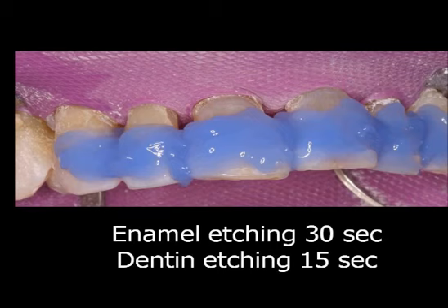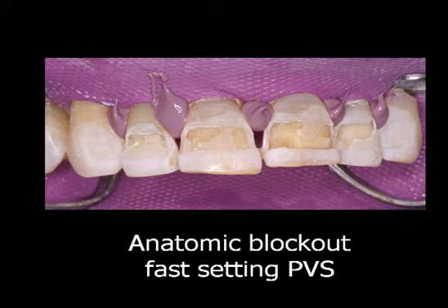We etch the enamel for 30 seconds, the dentin for only 15 seconds. After we've etched those surfaces, we'll then rinse and dry those surfaces, leaving the enamel frosty in appearance, and the dentin will be wet to leave it somewhat glossy. We've now placed an anatomic blockout of a fast-setting PVS heavy-bodied impression material. We get an anatomic blockout on these surfaces.